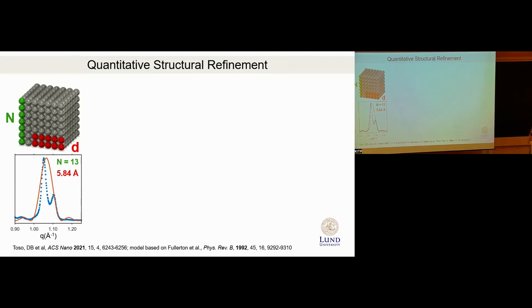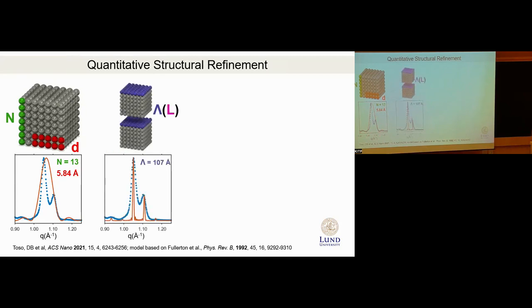There are 5 parameters in the model. First, we represent a nanocrystal as a set of diffracting planes. Each nanocrystal has a size, meaning there will be n planes separated by an interplanar distance. Each of these nanocrystals will give a diffraction peak, which would be broad because of finite size, and located at a certain Q position because of the specific d. Next, when you stack them in the ideal case without any disorder, you have interference due to this periodicity, which combines with this profile shape and gives you sharp periodic peaks.